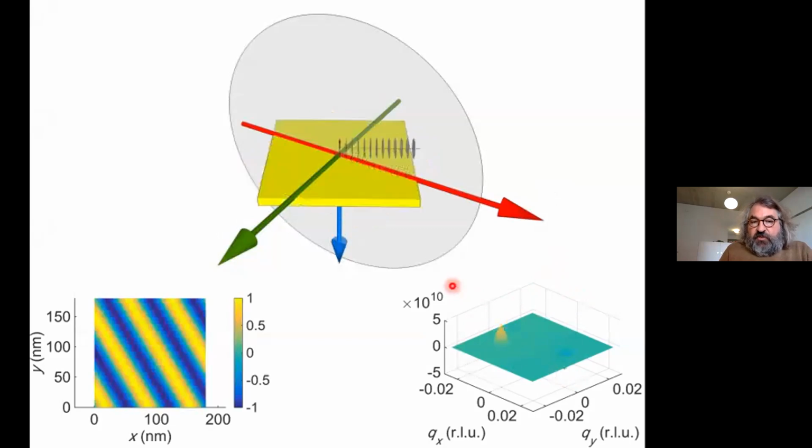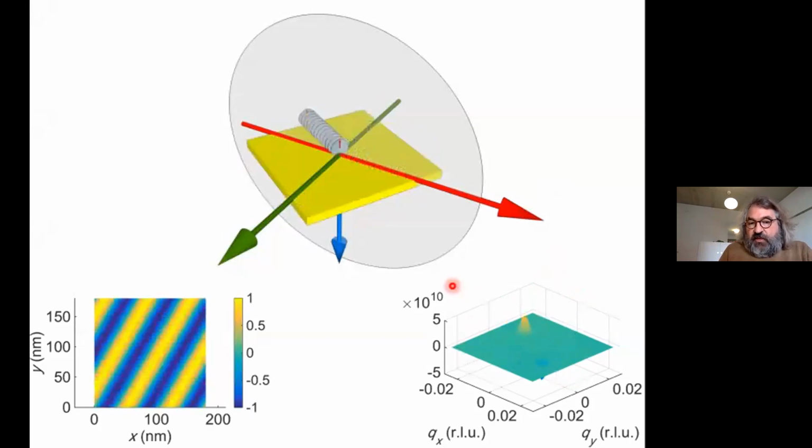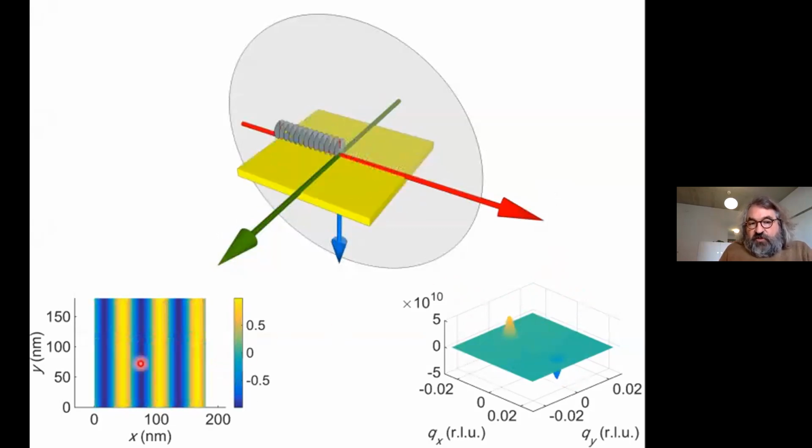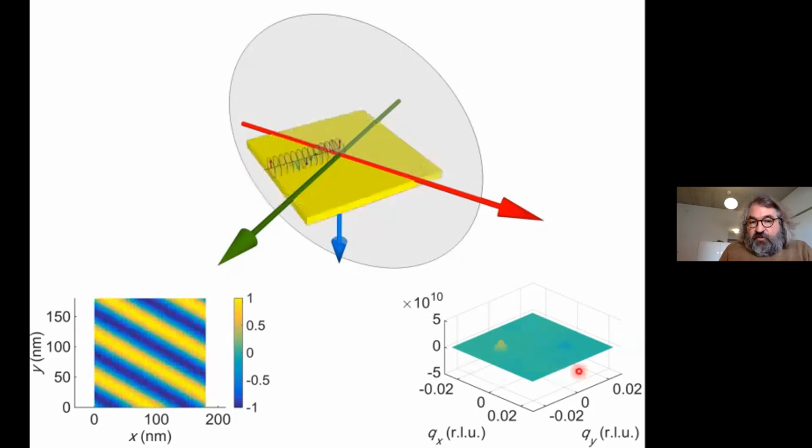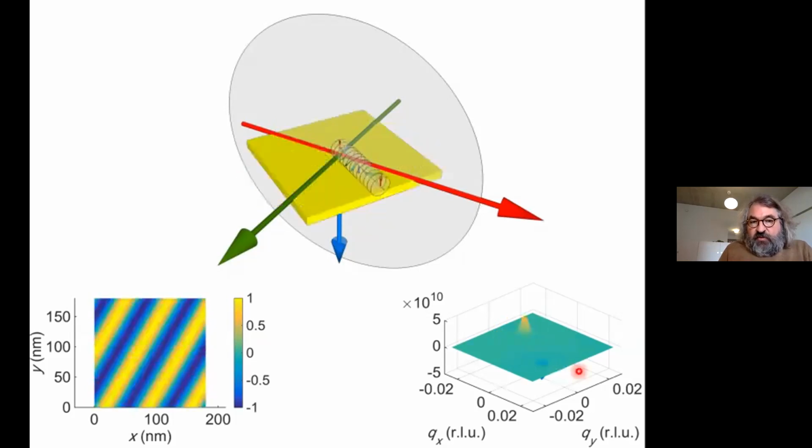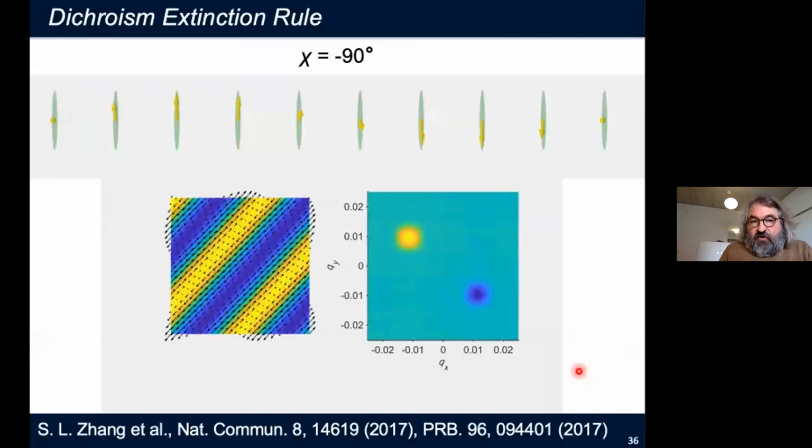Okay, let's start rotating. So as we rotate, we notice that the peaks, of course, follow the orientation of the lattice. So that's nothing new. But you can see that these peaks in the upper half, defined as above this line here, are yellow, meaning positive. And in the lower half, they are negative, meaning blue. So we can rotate that further. And we see how this evolves.